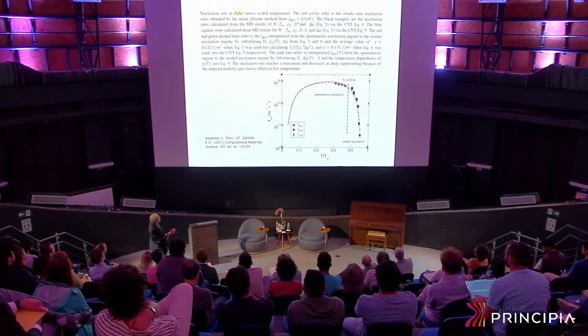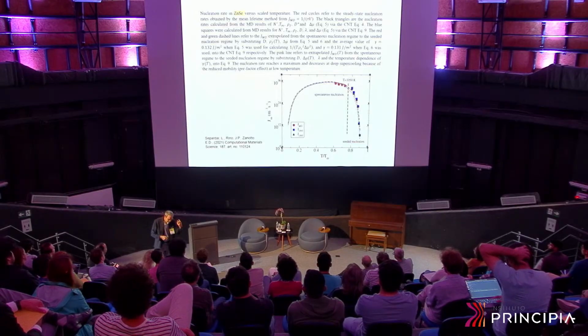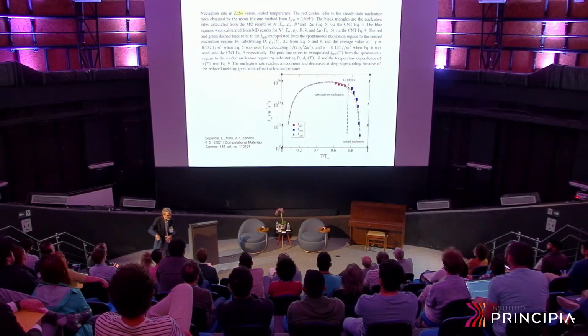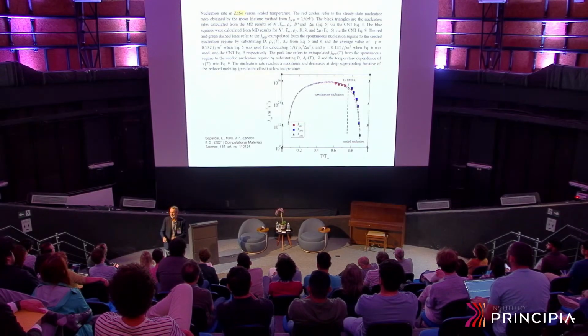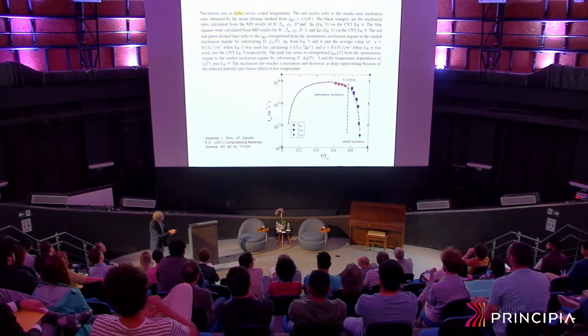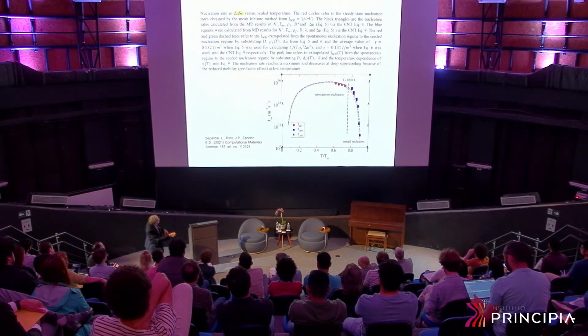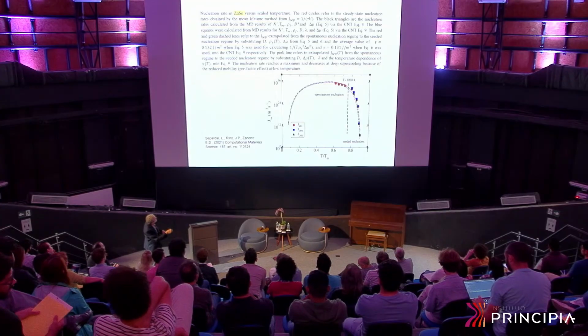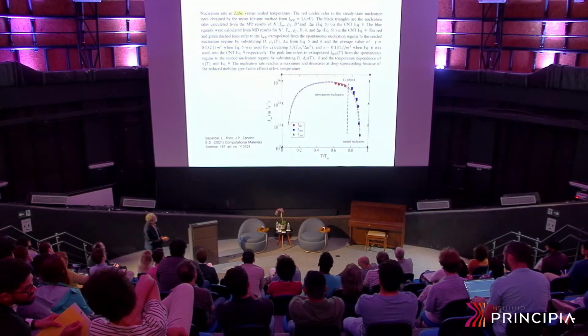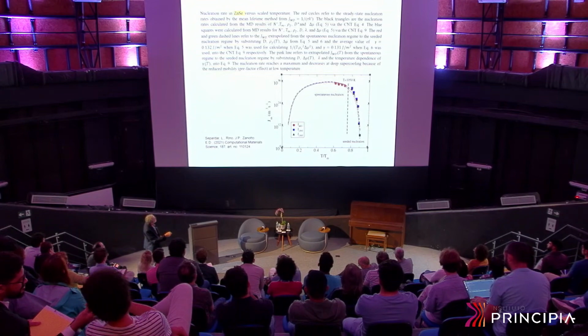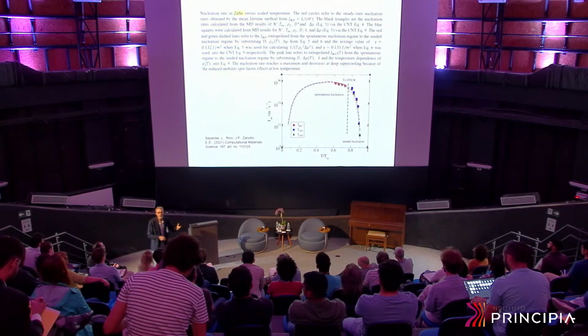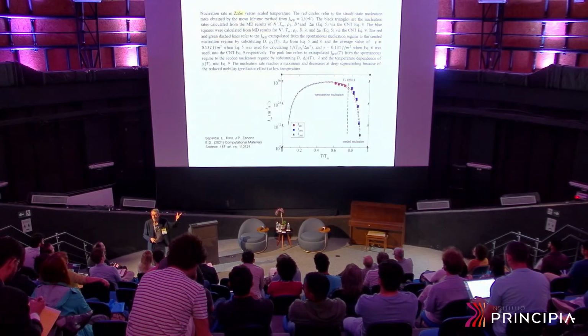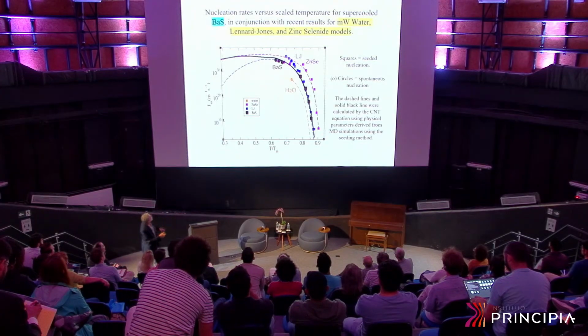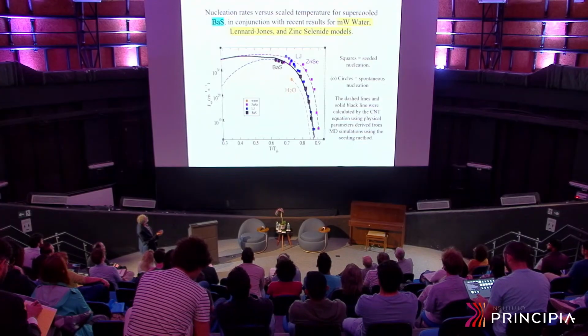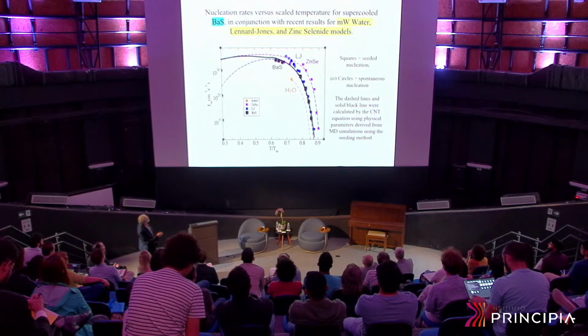And these are calculated by classical nucleation theory using parameters derived independently, like the diffusivity and the interfacial energy derived from MD simulations and plugged into the classical nucleation theory. This is a very, very nice description of nucleation rates within a factor of 2 or 3, which is nothing compared to the 50 orders of magnitude that we had. And for other systems, so zinc selenide, barium sulfide, etc.